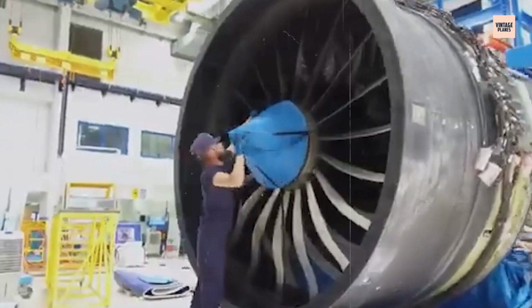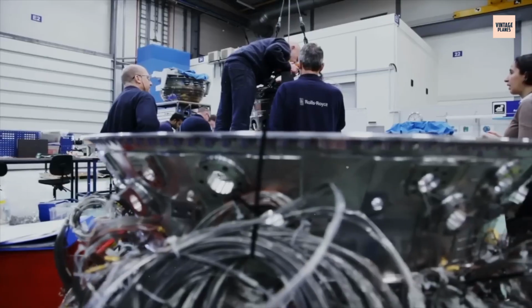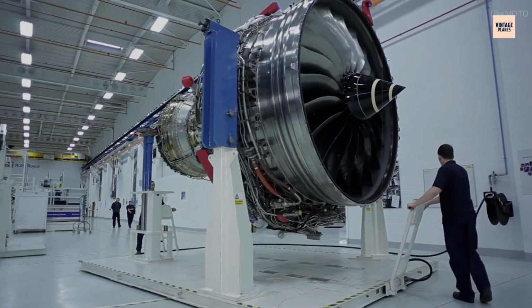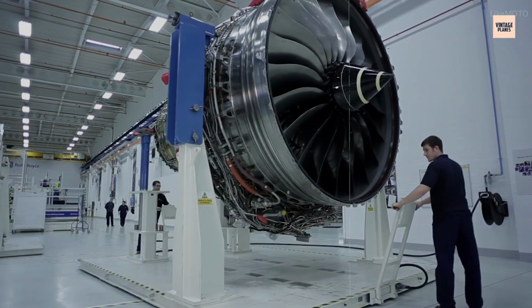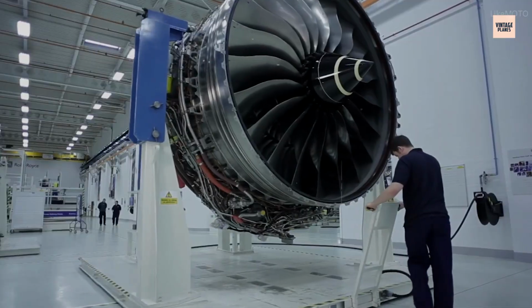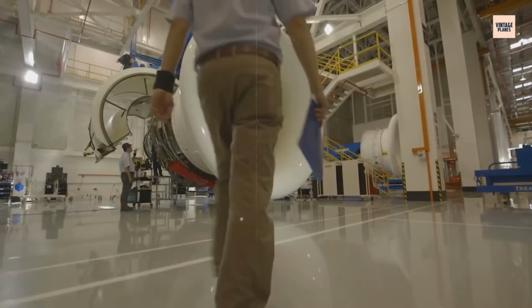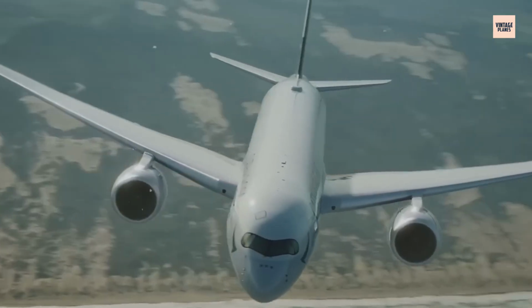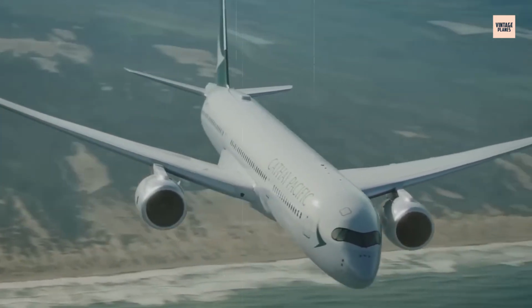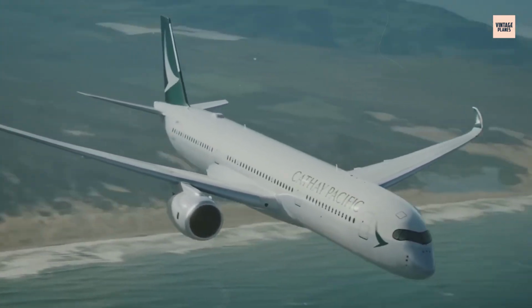Internal Rolls-Royce documents revealed that their manufacturing quality control had identified variations in this process. Some discs were being produced with wall thicknesses at the lower end of the acceptable range. While technically within specifications, these thinner walls created stress concentration points that could lead to premature fatigue.